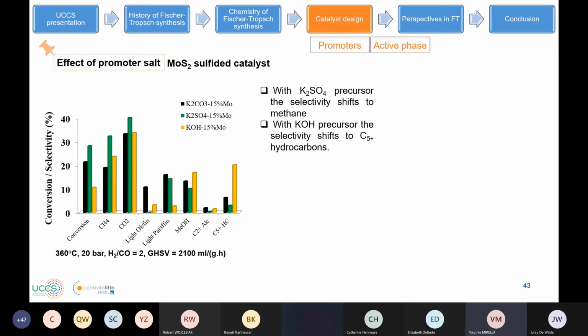But which potassium? Because there are different sources of potassium. So we use different sources of potassium and we observe the effect of those sources. We observe that we have an effect because when we use potassium carbonate, we have higher selectivity in olefin than, for example, if we use potassium sulfate. We have nothing. When we use KOH, we observe an increase in C5+ selectivity.